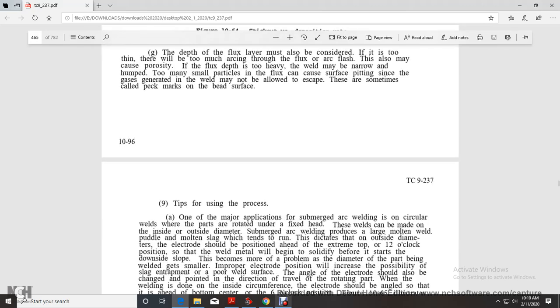Depth of the flux must be considered, whether too thin, causing too much arc through the flux or arc flashes, which may often cause porosity in the weld. If the flux depth is too heavy, the weld may be narrow and humped, with many small particles of flux surface pitting, since gases generated in the weld may not be allowed to escape. This is sometimes called a peck mark on the bead surface.